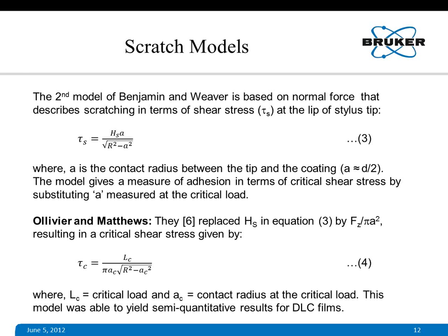Later on, Ollivier and Matthews modified the second model of Benjamin and Weaver, equation 3, by replacing Hs with Fz, that is normal force, divided by pi A squared. A is the contact radius, half of the scratch width. They gave an equation, shown as equation 4 here: tau c equals Lc by pi Ac root over R squared minus Ac squared. Lc is the critical load and Ac is the contact radius at the critical load. This model was able to yield semi-quantitative results for DLC film, diamond-like carbon film.